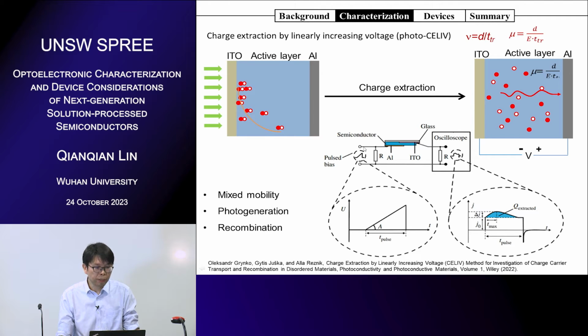And from this, if we know how many photons we use for the photo generation, and we know how many carriers we got from the transient, because this is the current density, if we integrate over time, we get the number of carriers. So if we know the carriers collected, and we know the photo generation, then we know the quantum yield of our device or semiconductor. This is the first thing: we can get the yield, or the EQE, quantum efficiency. And the second thing is we can get a very dispersive peak, and we know the peak here is the average or mean transient time for the carriers. Some carriers reach the contact electrodes earlier, and some get there later. That's why we get a dispersive charge collection.